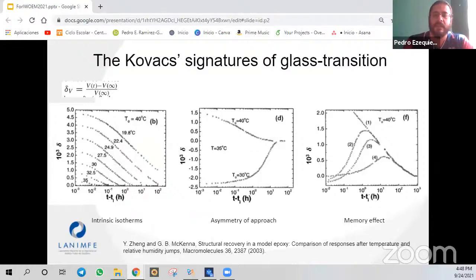Another important thing is that by directly measuring the evolution of volume, enthalpy, or fictive temperature, as Greg describes, through the variable delta, several important features of glass transition can be identified. These are referred to as the Kovacs signatures: the intrinsic isotherms, the asymmetry of approach, and the memory effect or crossover experiment. The intrinsic isotherms demonstrate a non-exponential decay of structural recovery and the shift in the equilibration time during an isothermal relaxation, as the temperature of annealing approaches the nominal glass transition temperature. The asymmetry of approach shows the non-linearity of structural recovery, and the memory effect, the non-exponential behavior of structural recovery and the dependence of the kinetics on the thermal history.